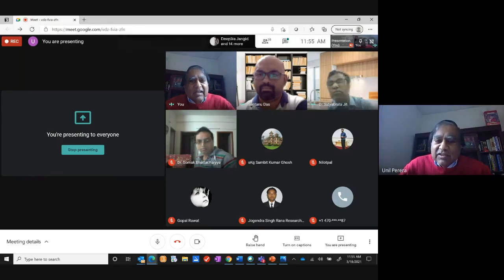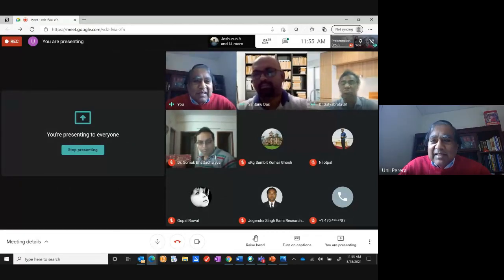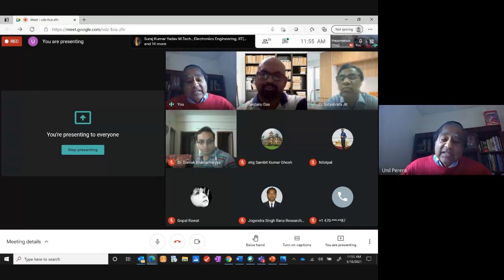So there is a tail. If you want aluminum gallium nitride in some region as the barrier and a gallium nitride region as the emitter, and you want a very sharp interface, and if the interface is not very sharp, there is a space charge effect. Then the barrier is going to get into the other material. When you apply a bias, the space charge is going to change things, and it is not what you have designed. So the energy gap is not going to be the same value. In fact, we started first using what we call homojunctions, where we use just gallium arsenide, doped across an interface.